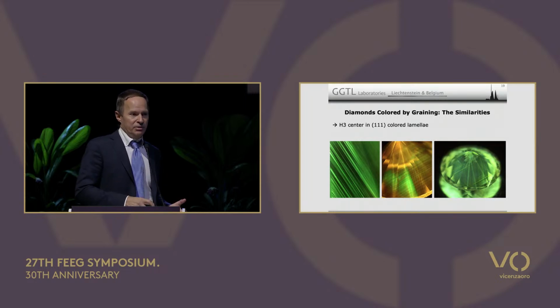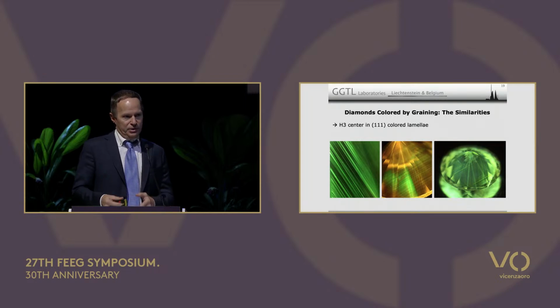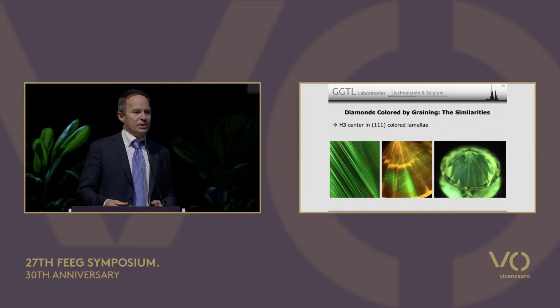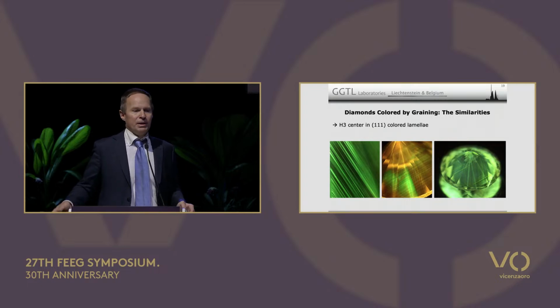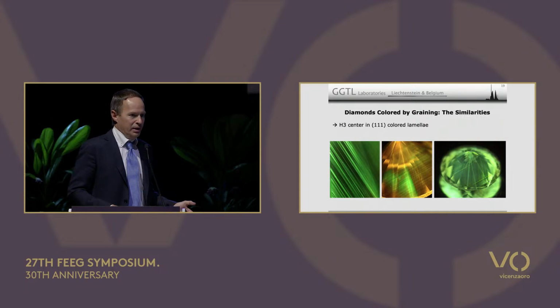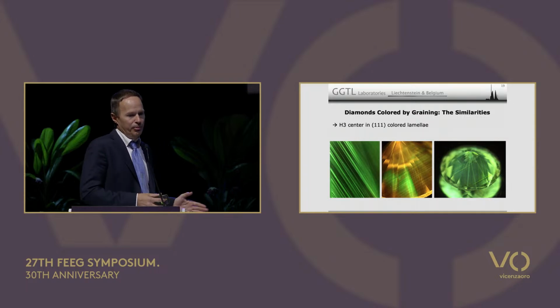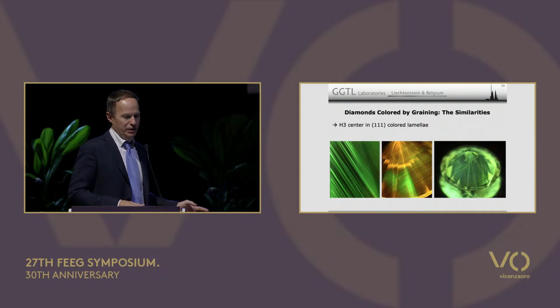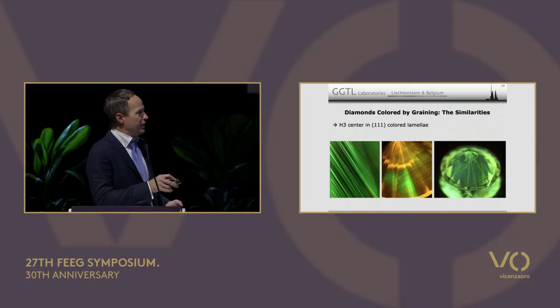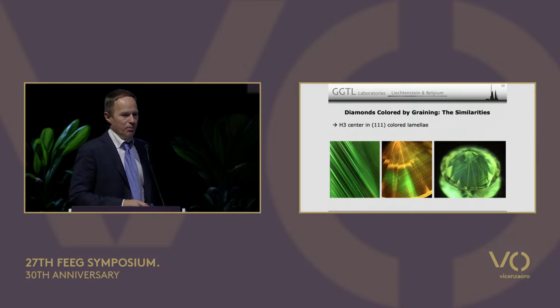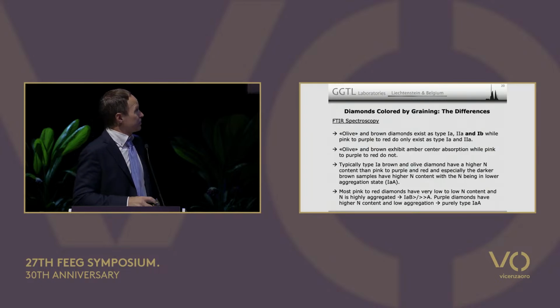You may not see the green fluorescence in a pink just by using a UV lamp, because the N3 center is extremely dominant. So in a pink diamond, you will see blue fluorescence. But on the other hand, if you use a laser in the blue wavelength, you will not excite the N3 center, and then you will see this green fluorescence popping up. So it's very, very common for deformed stones.